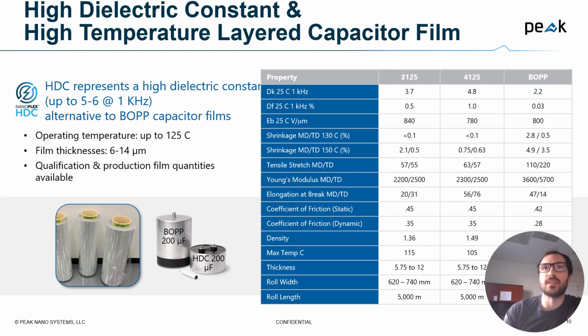There's a measurable increase in the dissipation factor. Now, I say that's not all that matters. You can play some tricks to improve your equivalent series resistance. However, for pulse power applications, when energy storage density really is your primary factor, this becomes an excellent material system compared to BOPP. And again, you can tune the properties between 3.7 and about 5-ish when we're looking at the different product ranges Peak Nano offers. And so again, you have that aspect of tunability for different material systems or needs in the power grid.